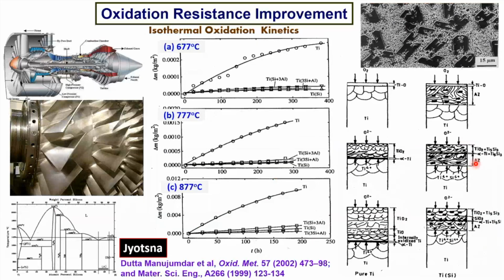Now, from there we shifted and raised the question as to why we should entirely depend upon oxides. Why can't we do it with metals or intermetallics? The clue can actually be obtained from an exercise we published many years ago, almost 25 years back, through Jyotsna Dutta Majumdar's PhD thesis. There we showed that when you develop a highly dense silicide microstructure, a silicide-embedded microstructure,